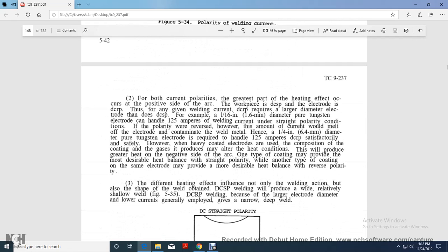For both current polarities, the greatest heating effect occurs on the positive side of the arc. With straight polarity, that is the workpiece; with reverse polarity, it is the electrode. For any given welding current, DCRP requires, a larger diameter electrode is needed than with direct current straight polarity. For example, a 1/16 inch diameter pure tungsten electrode can handle 125 amperes of welding current using straight polarity. With reverse polarity, however, that amount of current will melt off the electrode, contaminating the weld metal. Hence, a 1/4 inch diameter pure tungsten electrode is required to handle 125 amps of direct current reverse polarity satisfactorily and safely.